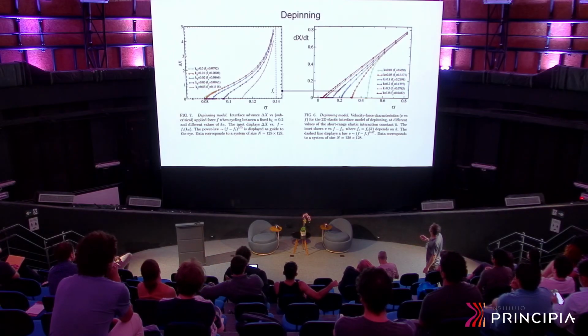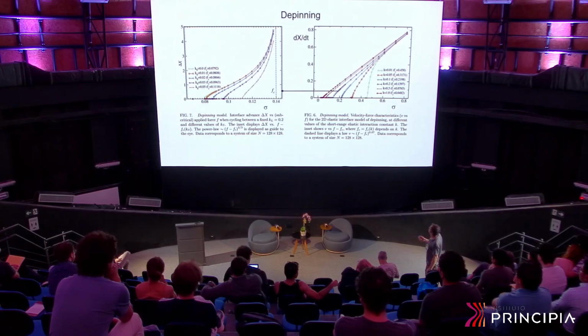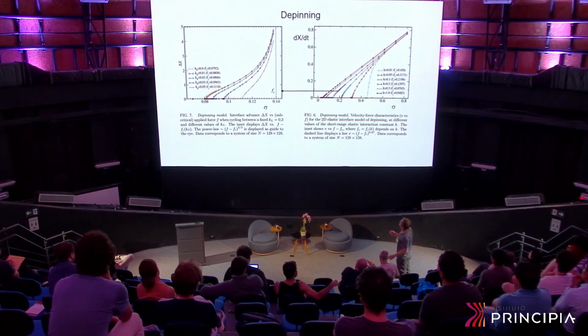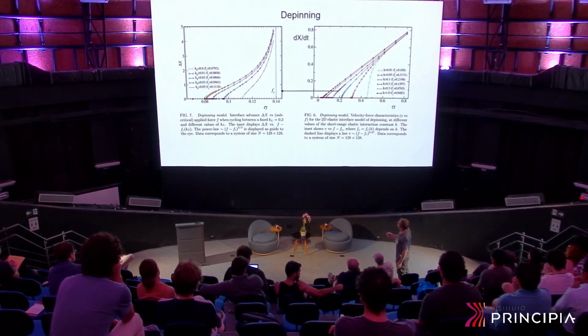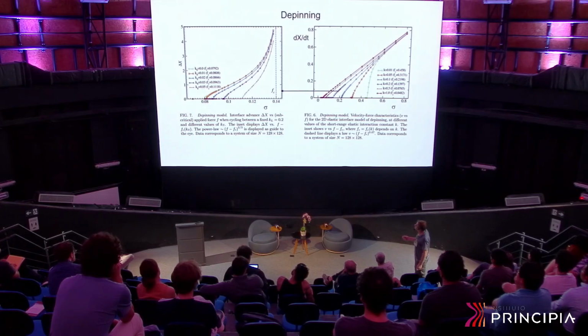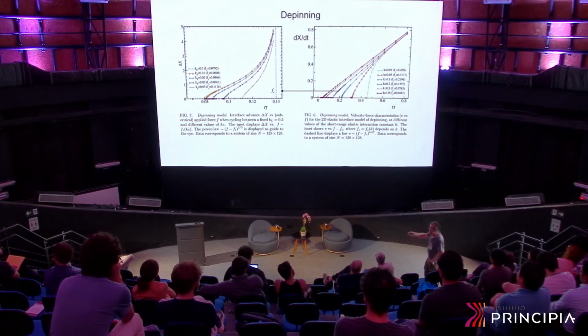If I take one of these curves, for instance the one corresponding to this value of K, and I produce this cycling effect, reducing K to a new value, K small, that is indicated here, and then back to the original value, and in this way many times, what we see is that below the value that was the critical force here, 0.14 more or less, we obtain a displacement of the system that is in fact linear with the number of cycles. The other point that is interesting to notice is that this behavior does not persist up to zero applied stress. It was a surprise for us to see that a kind of new critical stress appears, that is the value where these curves go to zero. And if we have an applied stress that is below that value, even in this regime of oscillatory spring constant, the system does not evolve.